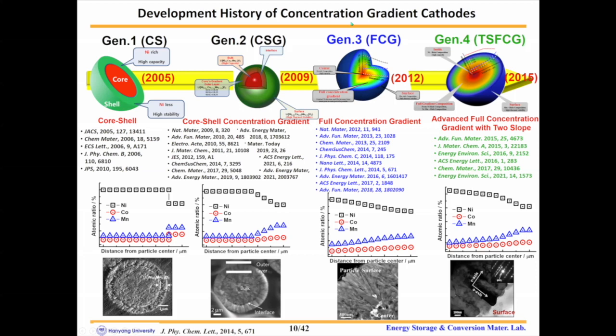This is the development history of the concentration gradient cathode materials. In 2005, we reported a core-shell material called generation one. As you can see, this is the concentration profile of transition metals. In the case of nickel, the concentration is kept at a very high level and then suddenly decreases at the particle surface. In 2009, we also developed the core-shell with concentration gradient materials. In 2012, we developed the full concentration gradient material, with the nickel concentration profile like this, and the manganese and cobalt profiles like this one. Three years later, we developed the advanced full concentration gradient with two slopes.